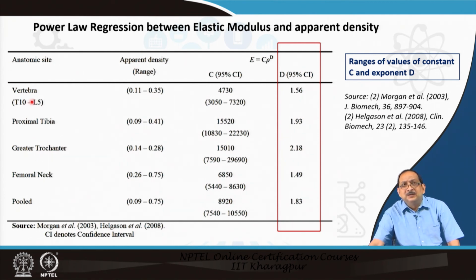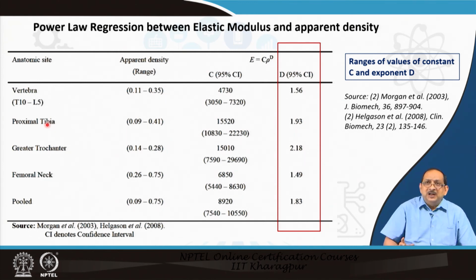the power law models, which quantify the relationship between elastic modulus and apparent density of different anatomic sites. So, you can see that the anatomic sites vary from vertebra, proximal tibia, greater trochanter, femoral neck, and a pooled data set, and the range of values of the constant C and the exponent D is presented here in this slide. The variation of exponent D is very clearly presented, and it clearly shows that the relationship will vary with the anatomic sites. So, there is no single E to rho relationship; it varies from one anatomic site to the other, one bone to the other.